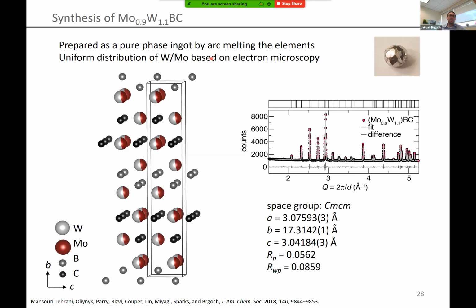You melt all of the elements together and you end up with an ingot that looks like this, a really nice, shiny, well-faceted product. Breaking this apart and doing electron microscopy shows that we have uniform distribution of the tungsten and molybdenum atoms. Collecting powder X-ray diffraction shows that we're able to make a really nice phase pure product.